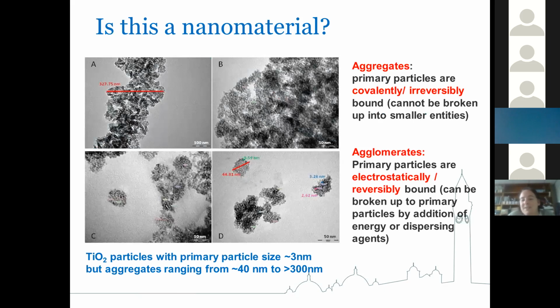There's also quite a bit of confusion in the literature as to what is an aggregate versus what's an agglomerate. ISO, the International Standards Organization, came up with some agreed terminology, but it's not always used consistently. Technically, an aggregate is where the primary particles are covalently, so chemically and irreversibly, bound and cannot be broken down. Whereas an agglomerate is where an environmental change has caused the particles to agglomerate, and that usually can be reversed. So technically, most of the changes that I have talked about before, when they go out into the environment or are released from a product, should be considered agglomeration rather than aggregation.